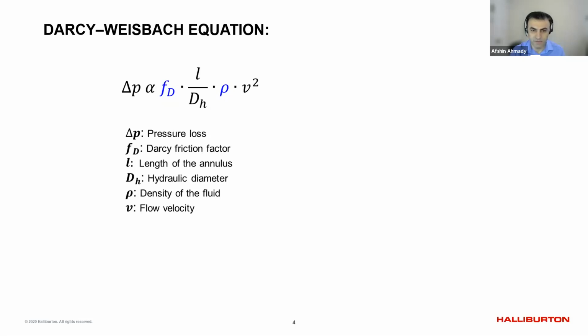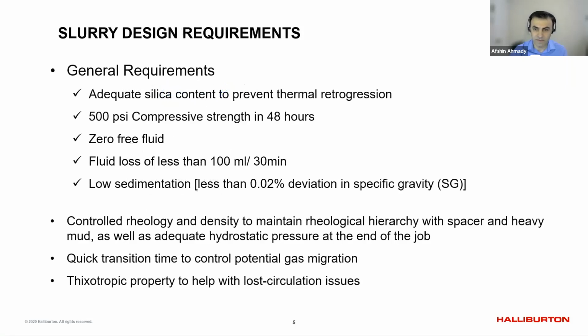On this project, we tried to reduce the viscosity, but at the same time we needed to maintain the cement properties, including free fluid, fluid loss, and sedimentation, and all of them are impacted by reducing the viscosity. So how can you maintain the cement properties? Just by holding the yield point high, so that when the cement goes static, it is not losing its properties and ending up with free water, fluid loss, and sedimentation. But at the same time, you could bring the plastic viscosity down. When cement is in motion, you have some assistance from the motion, and you decrease the ECD while pumping cement. Once the cement goes static at the end of the job, mainly, it has a high yield point to hold the particles in place and hold the properties of the cement.